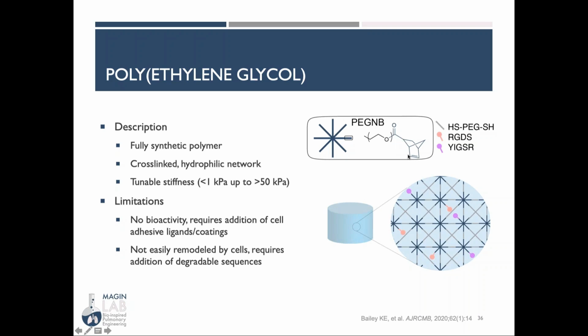This is just an example of a PEG network where we can put in PEG norbornene multi-arms and then cross-link it with a dithiol PEG crosslinker and add in binding moieties like RGD and YIGSR that mimic fibronectin and laminin inside the body.